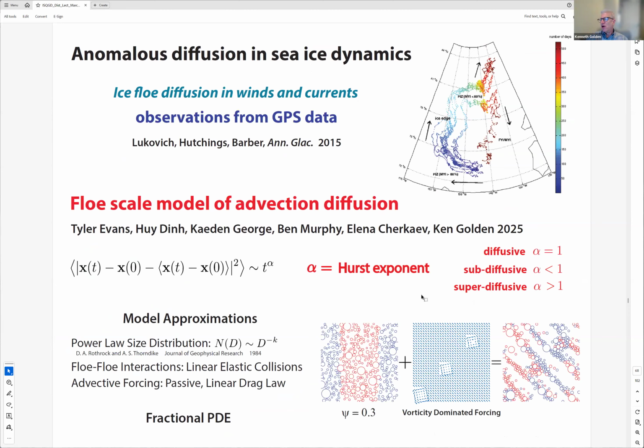Okay, finally, the last thing I'll talk about is what's going on on the very big scale. One of the really interesting phenomena that I came across was looking at GPS data of ice flows, and they undergo something like Brownian motion. However, it's not just Brownian motion. They exhibit anomalous diffusion with a Hurst exponent bigger than 1 for superdiffusion, less than 1 for subdiffusion, and alpha equal 1 for pure diffusion. And we've developed a floe scale model for this, where we can start to mimic this type of behavior.